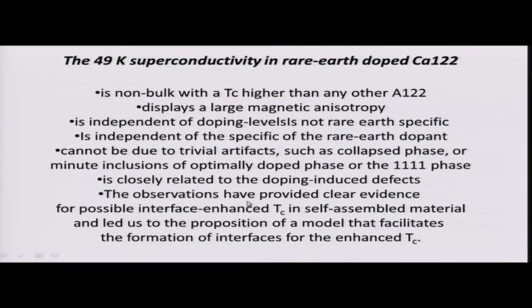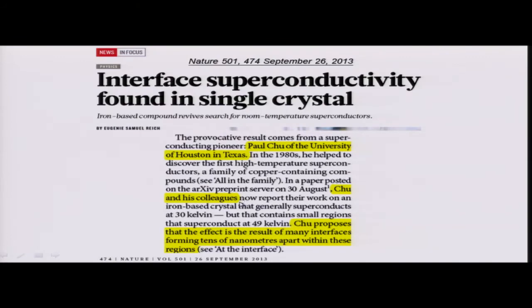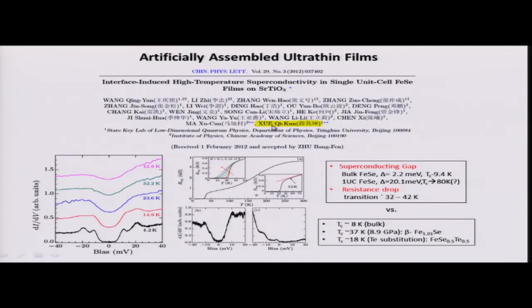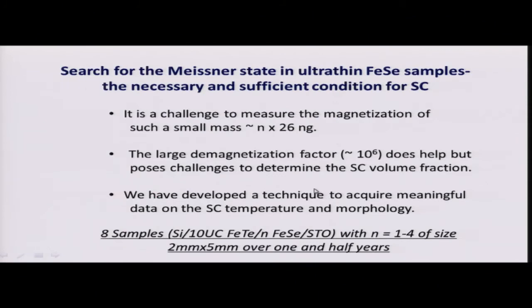The 49 K superconductivity is very unusual, and therefore it's consistent with the so-called interface enhanced superconductivity. So therefore, its superconductivity may be found in these single crystals. And then the other is Xue's results on this. And they announced it goes very high. The transition temperature originally is something like 40 degrees. But unfortunately, in that case, the material was measured basically using the tunneling method, and they saw an energy gap. They saw a gap exist up to 60 degrees Kelvin, by different people in China. And now the question is, is that gap really superconducting or not?